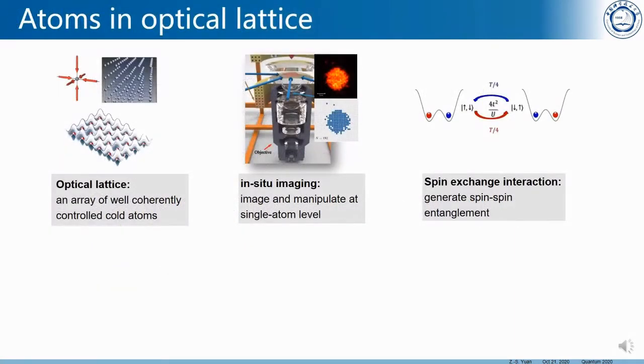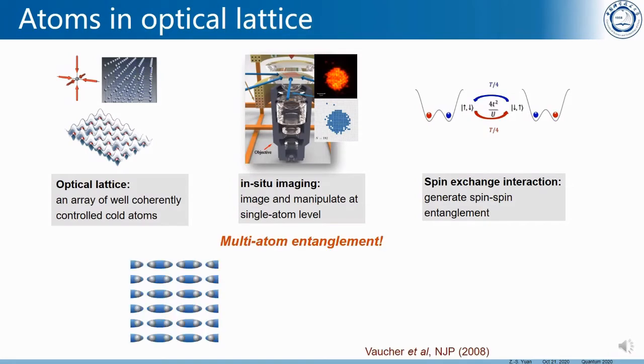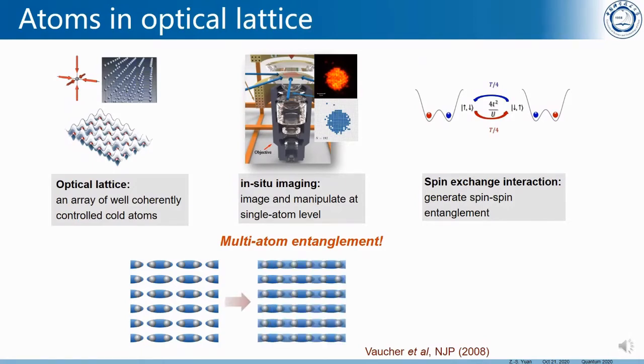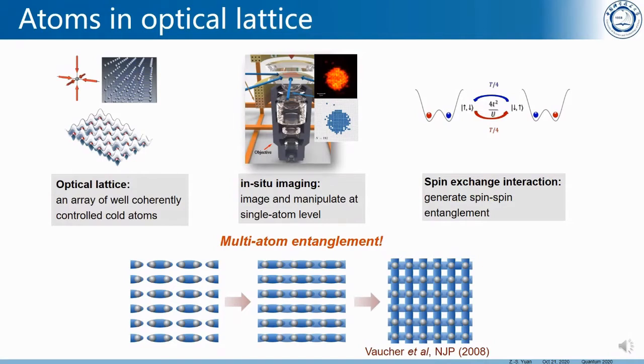With the technique of optical lattice, we can prepare a large number of atoms in a single run. Each site of the lattice is occupied by a single atom. With quantum gas microscope, we can do imaging and manipulation at single atom level. By tuning the interaction between atoms in neighboring sites, we can create entangled atom pairs. After we have entangled pairs, we then connect them along this chain and afterwards along the vertical direction. Finally, we have a large entangled state in a two-dimensional optical lattice.